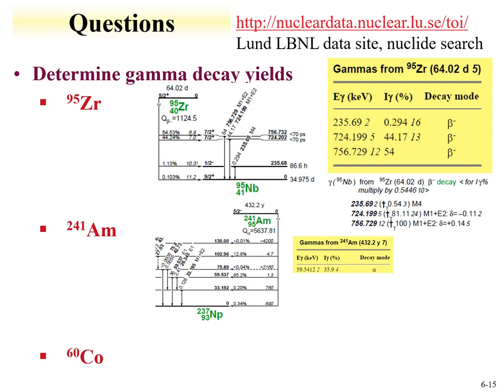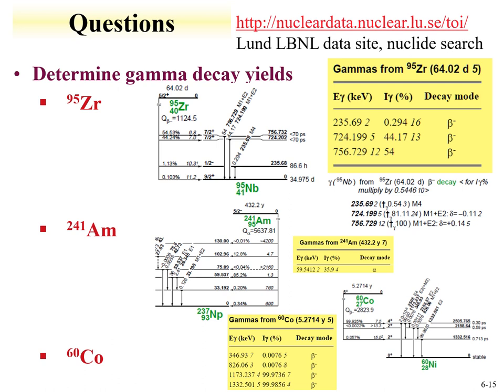Another example could be cobalt-60, again from the LBNL site. We get the data. We see that there are two intense photopeaks, each one above 1000 keV, and yields on the order of 99%. And what this looks like from the decay scheme, this cobalt-60 beta minus decays to a 4 plus state 99.925% of the time.